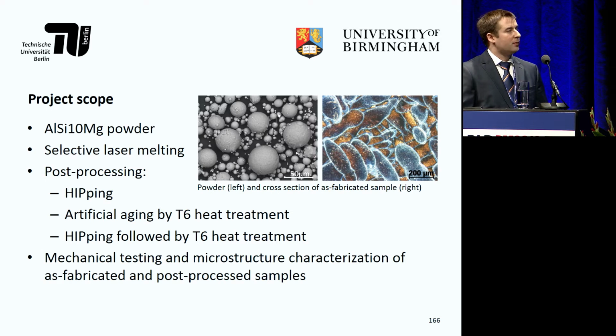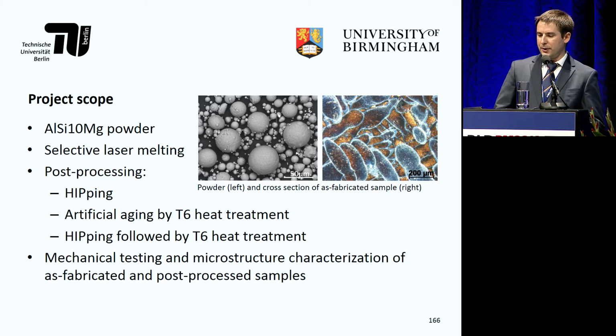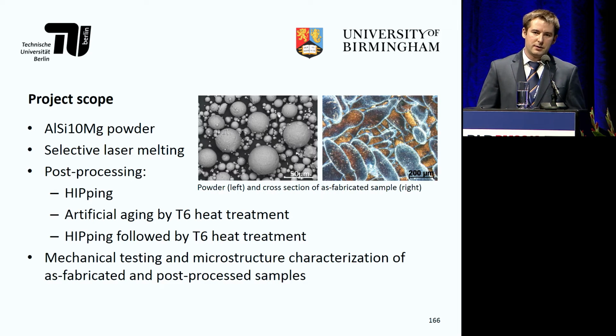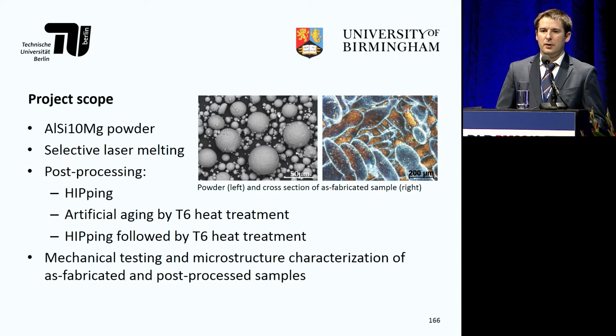My project scope: I received AlSi10Mg powder, and I performed selective laser melting to obtain samples. With these samples, I did post-processing to compare with as-fabricated selective laser melted samples. One batch of samples was hot isostatic pressed. A second one was artificially aged by a solution and aging heat treatment. And a third batch was first hot isostatic pressed and then T6 heat treated. With these 4 batches of samples, I performed tensile testing and microstructure characterization to compare the different conditions.